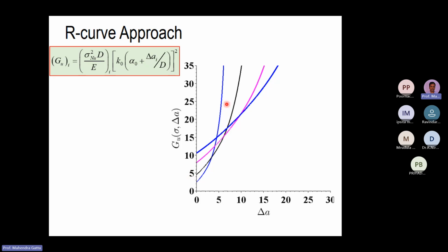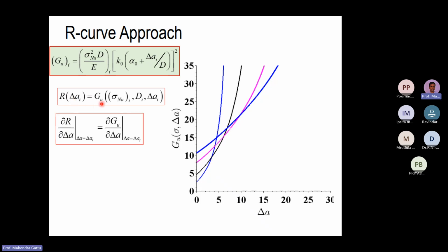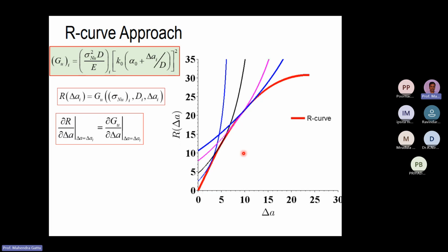Now the R curve is called the crack growth resistance curve. The unique property of the R curve is that it touches all these GU curves, and it touches each at only a single point. So there are two conditions it will satisfy. One is that it touches these curves, and the other is that it touches at a single point. That means at the point of intersection, the slope of the R curve will be the same as the slope of the GU curve. So effectively it will look something like this. This is the crack growth resistance curve.